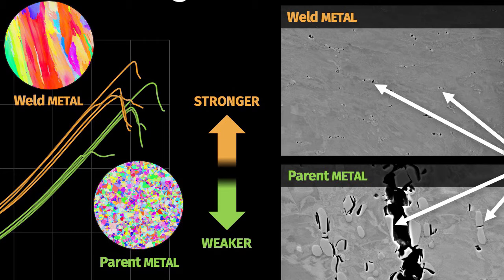So this is at the macro scale, but if we want to understand this behavior, we have to always look into micro scale. And we found here on the right hand side, we can see that in the parent metal, we have these particles which are failing and propagating the crack. While in the weld metal, these particles are significantly finer. And this is one of the reasons why the weld metal is actually stronger than the parent metal. So this is great. We found that the weld metal is strong enough, but this test tells us nothing about molten salt corrosion performance. So in the next step, we're going to do a molten salt test and find out whether this weld can be used in the molten salt environment.